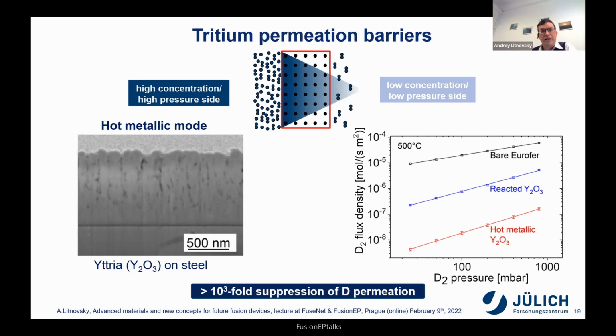How can it be done? By means of so-called tritium permeation barriers. The barriers should be impermeable to the tritium atoms. On the high pressure, high concentration side, like the plasma side, there will be a lot of tritium. After the barrier there should be very few. It is realized with a quite tiny 500 nanometer thick yttria layer deposited on the steel, because steel is the structural material which is located after the tungsten.